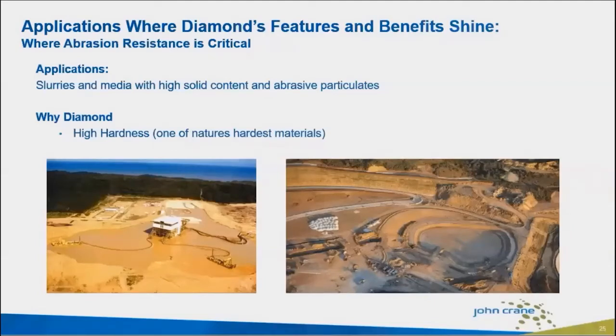So why diamond? Just to drive the point home again, due to its extreme high hardness. Note here that, as I mentioned, our diamond is optimized to run against any counter hard face. However, when using diamond as a solution to challenging slurry applications, we do recommend using diamond versus diamond on both seal faces so that you get the benefits of diamond's abrasion resistance.